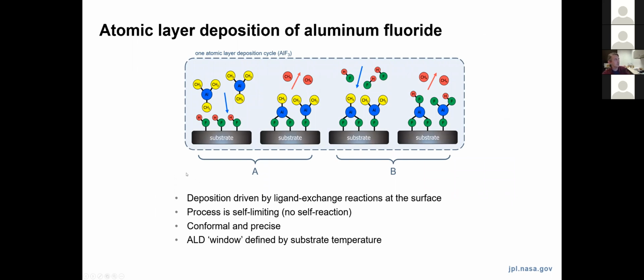And so what is atomic layer deposition? ALD is a special case of chemical vapor deposition, which is driven by self-limiting reactions of precursor chemistry that you're using in the process with the substrate you're trying to coat. And so this is a pictorial example of an ALD process for aluminum fluoride. But sort of the magic of ALD is this self-limiting property.